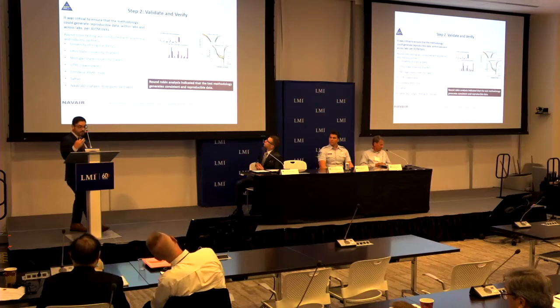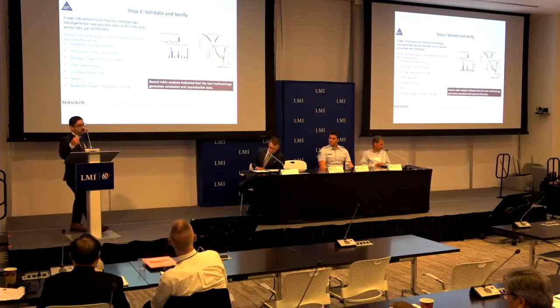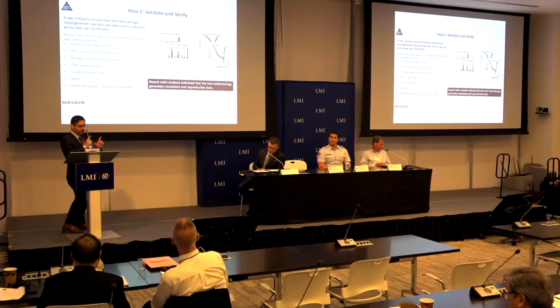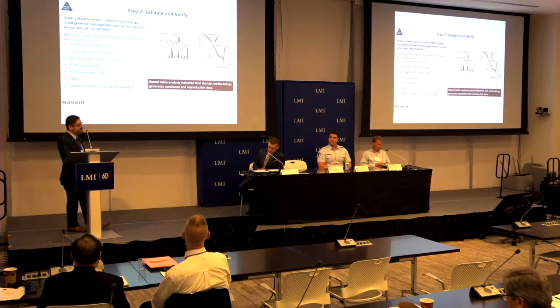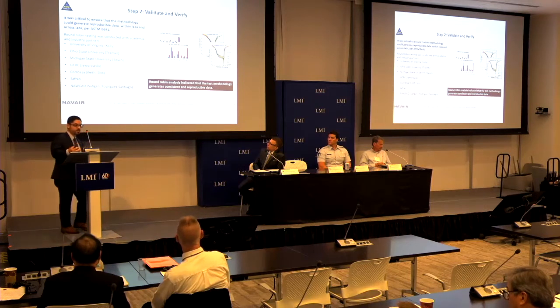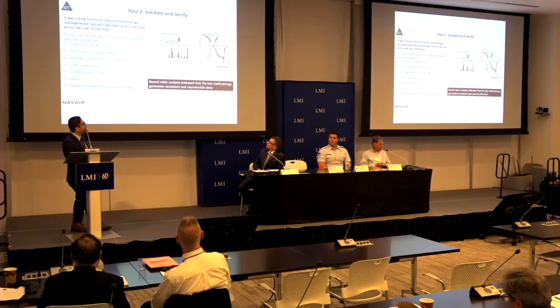And again, as I mentioned, this was a big effort, and we included academia, industry, and of course ourselves in the Navy to generate this data. And these were the partners for this round robin, right? So we gave that standard on how to generate data, and we said here it is, generate data. Everybody came back, we processed it, we analyzed it, and at the end of the day, we concluded through the round robin that the methodology would indeed generate reproducible data. So that was a critical step in there.